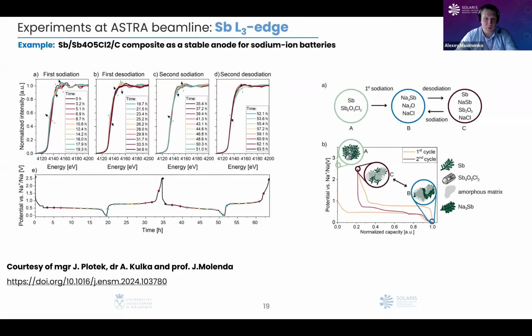and we penetrate this battery with the X-rays and investigate how the local structure of antimony changes during the charging and discharging of such a battery, where we have such a complicated composite as an anode material, and as a cathode we had sodium. Investigating such spectra, we managed to understand what kind of processes of alloying and appearing of new phases of antimony occur during charging and discharging of this battery, and it proved that such a material could be a really stable anode for future sodium ion batteries.